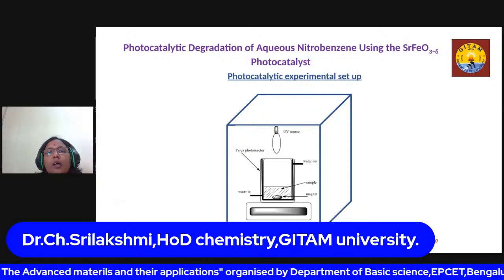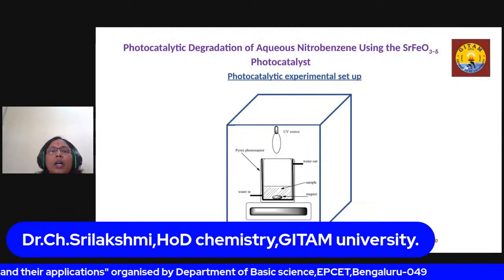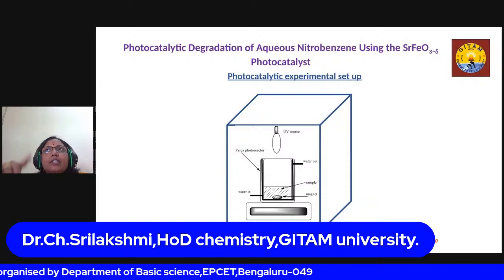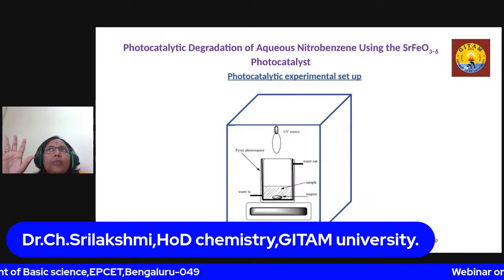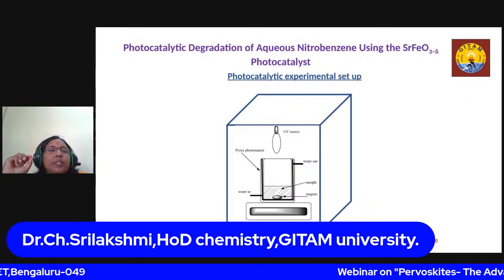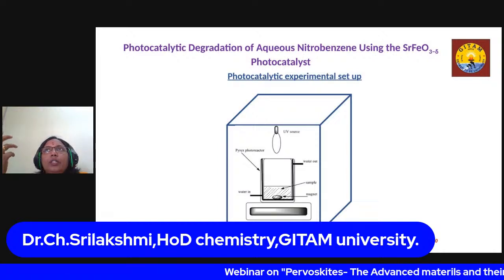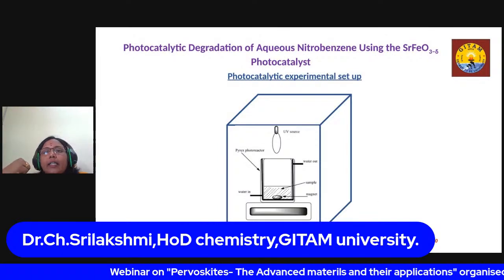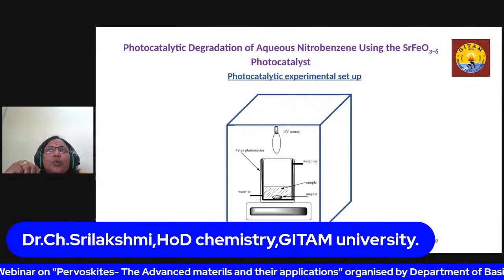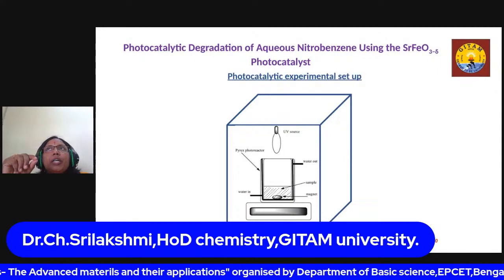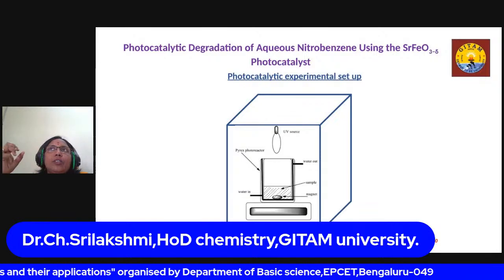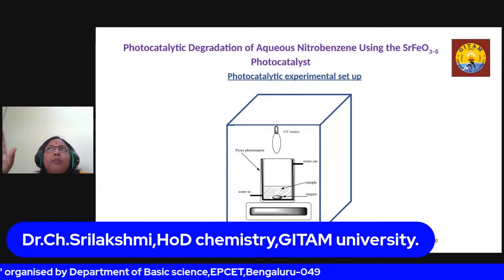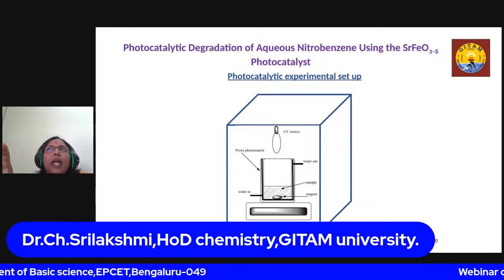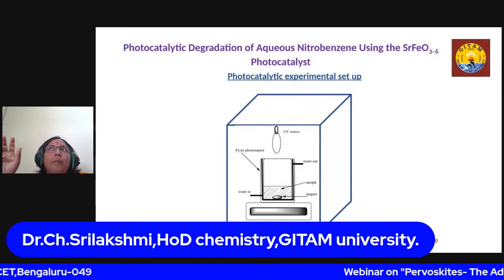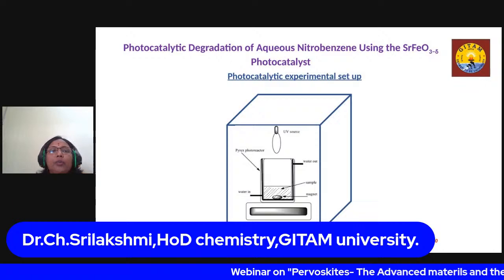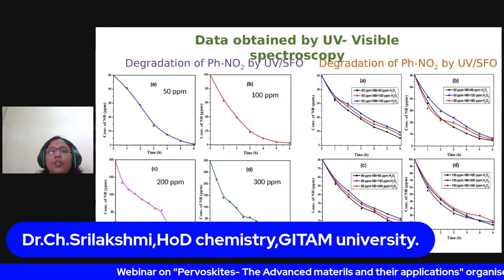Prior to UV irradiation of the sample, we stirred the reaction mixture at room temperature in the dark for 30 minutes in order to attain adsorption-desorption equilibrium between the catalyst and the reactants. After that, for kinetic studies, 5 ml of the reaction mixture was taken at regular intervals after UV radiation and analyzed with a UV-visible spectrometer, and the unknown concentration was obtained using the calibration curve of the UV-visible data.